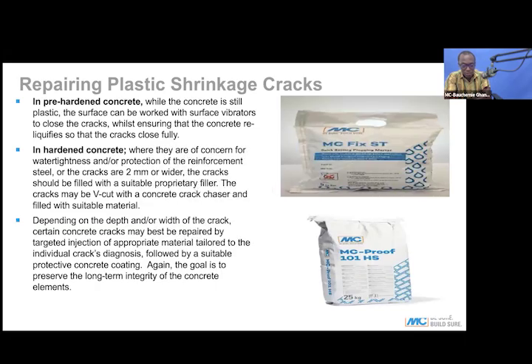How do you repair this kind of cracks? Sometimes you have to open the cracks, because some of these cracks are not deep cracks. They are just surface cracks. So we can just open the surface by cutting into a V shape. Then you repair with cementitious materials which have the same strength as the existing concrete. In some cases, you can use resin materials. You can use an epoxy material. You mix the epoxy with sand, then you can use it to seal the crack. All these are ways you can repair these cracks.